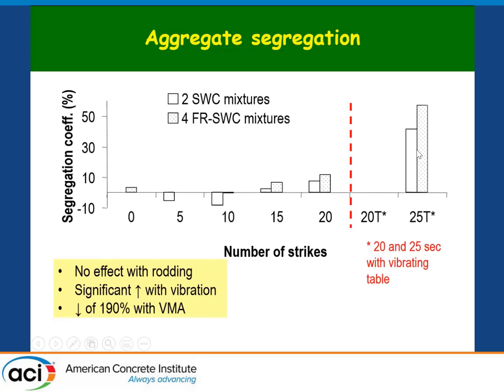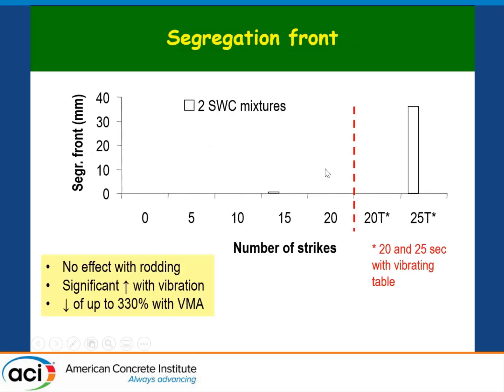But that number also, for the super workable concrete with fibers, increases, but then it can be reduced when you are using VMAs. So in terms of mechanical properties, we saw that the vibration is advantageous, but we could see that if the concrete is not stable, then vibrating the concrete is not a good idea because you could get into some segregation issues.